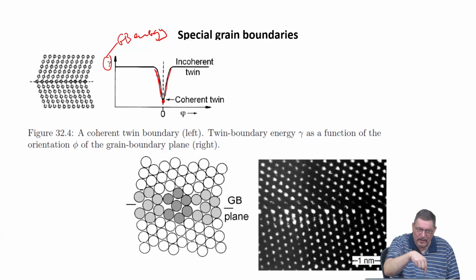But normally you have to go to each specific boundary and then you can look really at both the misorientation angle of the two grains as well as the inclination of the boundary. You get the full description, but you can only do this boundary by boundary. You don't get it in like the total summary, so it's more work. But in EBSD data, this is one of the informations you get for each and every boundary.